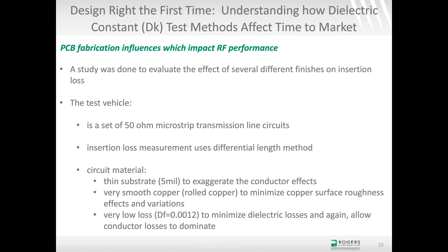Then we used a very smooth copper, rolled copper, and that means there's going to be less circuit-to-circuit variation due to the surface roughness variation. And then we also used very low loss materials, DF about 0.0012. We did that to, again, minimize dielectric losses and exaggerate the conductor effects. Again, we're trying to see the difference of conductor effects of these different final plated finishes.